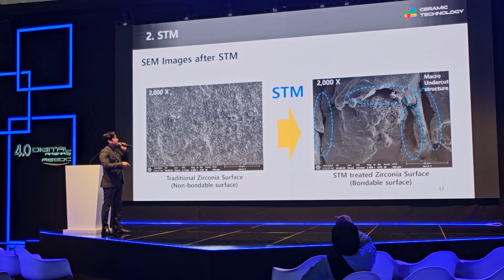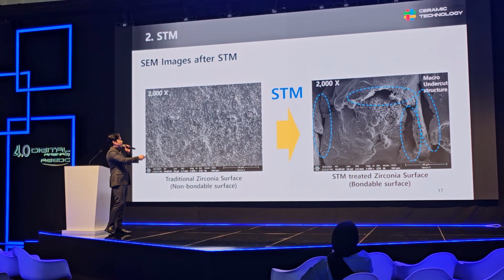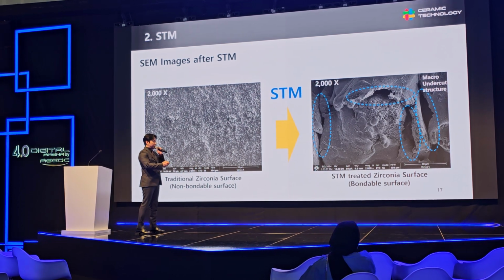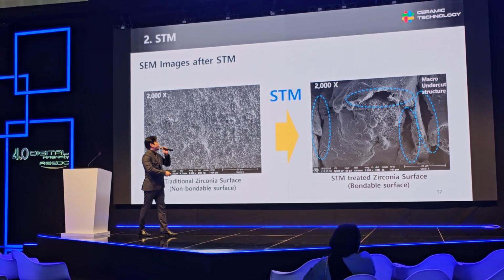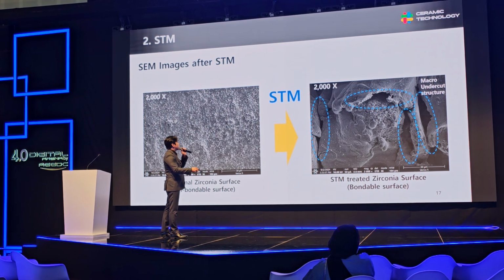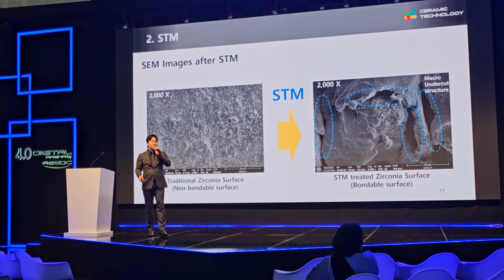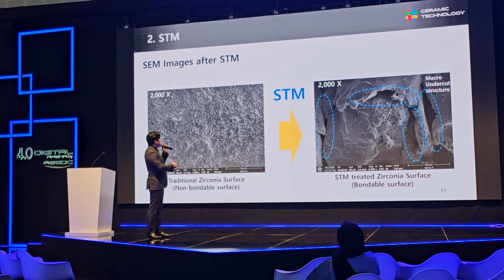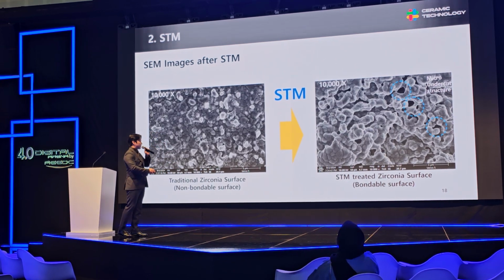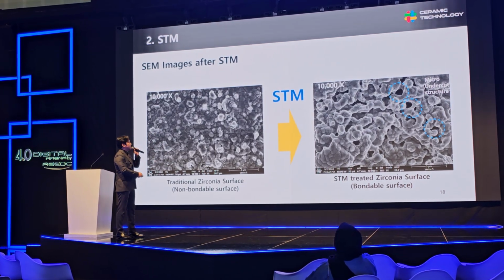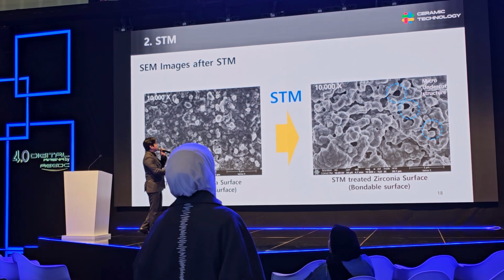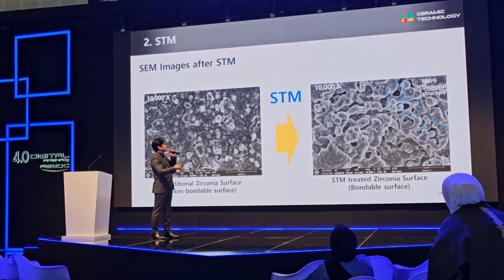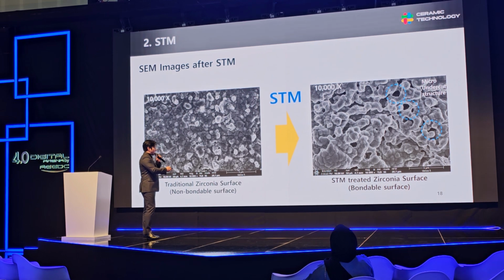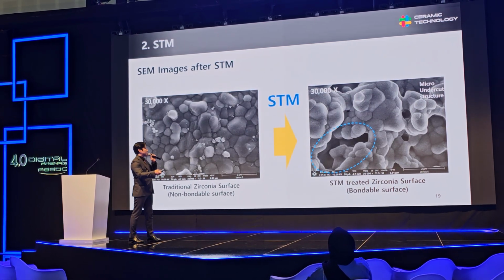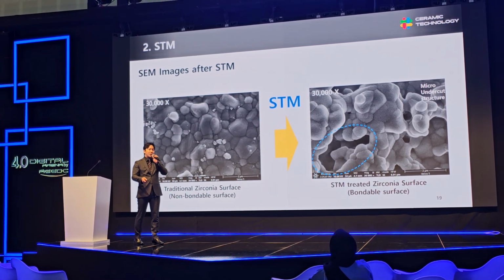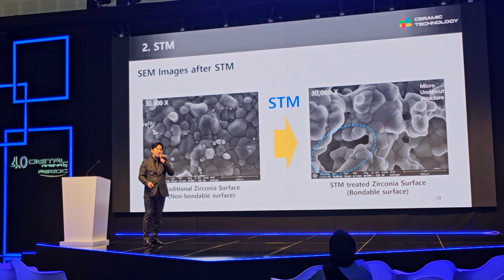And this is the 2000 times magnification image. As you can see, the black areas. After this treatment, some macro structures are created, and it maximizes the macro retention with the resin. And let's zoom in further. At 10,000 times magnification, as you can see, the micro structure is created. And this microstructure's size is approximately 2 micrometers, so the micro-retention is maximized after the STM treatment.